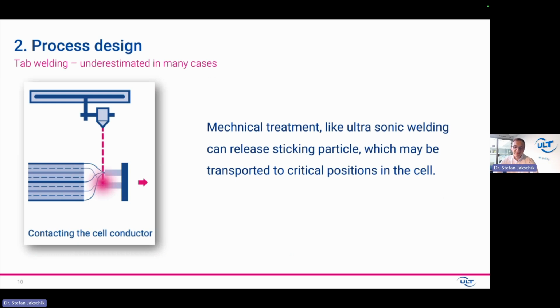Further on, when you put everything together in the pouch, you have a tab welding process. To my experience, this is the most underestimated process because very often it's done by ultrasonic welding or laser welding, and many people don't see the particles, and I very often hear from the market there are no particles in that step. This is not true. When we do a particle analysis here, we also see a lot of particles, especially since you also move particles from previous production steps and bring them to very critical positions in the stack or in the cell.